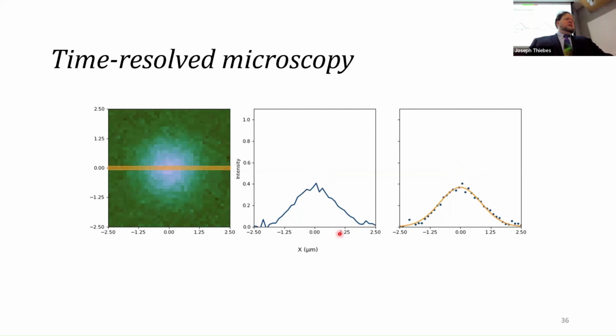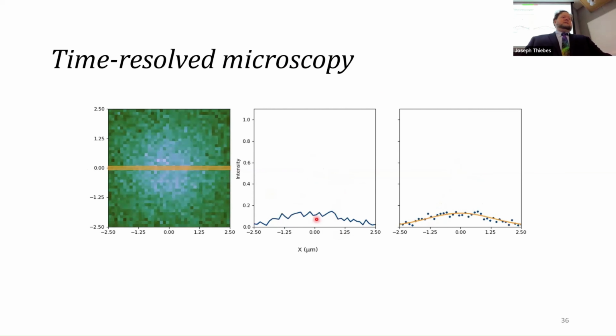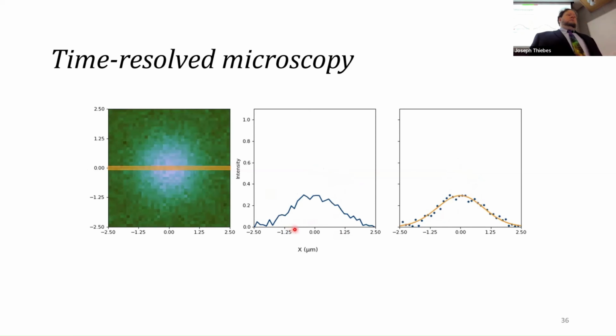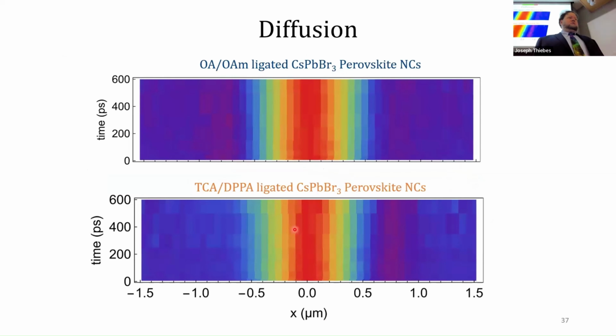And also, if we take each of these time slices and consider plotting it in a different way, that's what we've got here in this rainbow plot. Basically the red part is the top of that peak, and the blue part are the tails of that. And this is plotted over time. So if you look at a slice at the bottom, that's at time 0. And as you move up, you're moving forward in time. And so if you have diffusion, then you should see this peak spread out. And in this plot here, if you squint your eyes, you can see a little bit of that happening with this other ligand, the TCA-DPPA, which is the conjugated ligand.